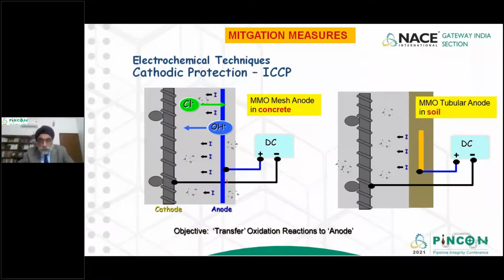When you put in a mesh within the concrete, we get a uniform current distribution because the mesh anode is very close to the steel rebar. When we are putting in an MMO tubular anode in soil, the design has to be proper to ensure that there is a uniform distribution of current on the rebar. Otherwise, the impressed current system will not work properly. Only a certain element of reinforcement will get protected, and the other areas of rebar will not get protected. So for soil-based anodes, the proper design has to be done to ensure a uniform distribution of current in the concrete structure.